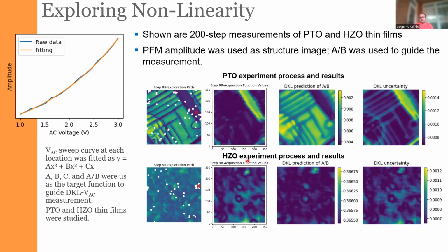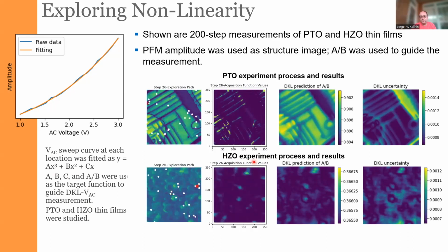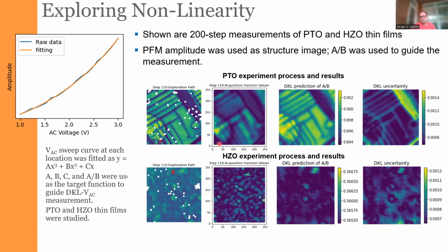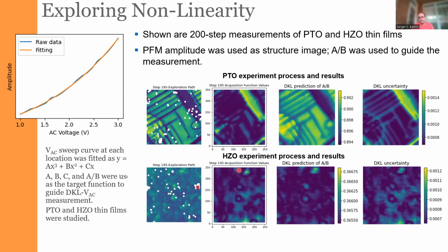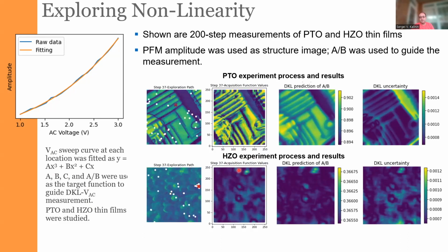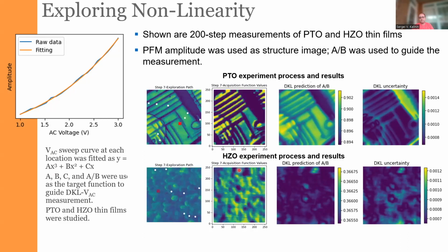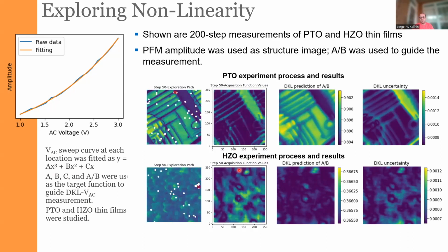Another example is hafnium oxide. A very interesting material, the first binary ferroelectric. When the first papers about it were published about 10 years ago, nobody believed that a binary oxide can be ferroelectric, but it is, and now it's probably one of the biggest developing areas in ferroelectricity because these materials are compatible with the silicon backend fabrication. In other words, you can use it for FRAM, unlike the normal ferroelectrics.